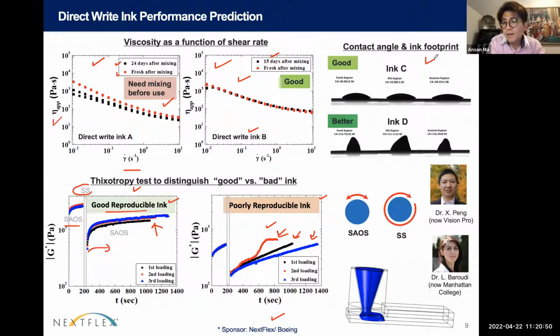As I promised you before, and also I highlighted before, in addition to rheology, surface science, or the contact angle is also very important. So let's say if you are looking for a very good, high resolution print, how the ink wets the substrate matters. If you have 2 cases, for example, here, you see in one case, ink C is a very nice hemisphere, because you have surface tension, right? And this ink is trying to make a contact angle with the substrate. Depending on how you clean the substrate, the contact angle could vary. That's key point number one.